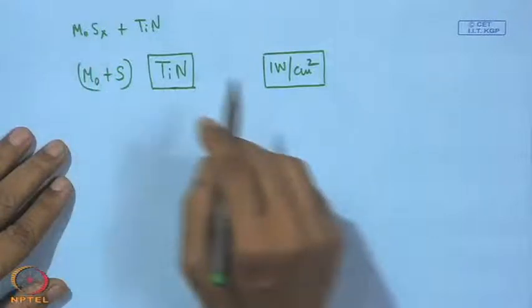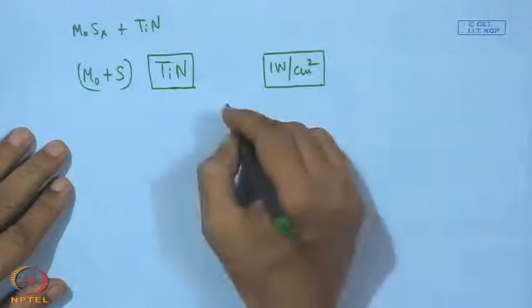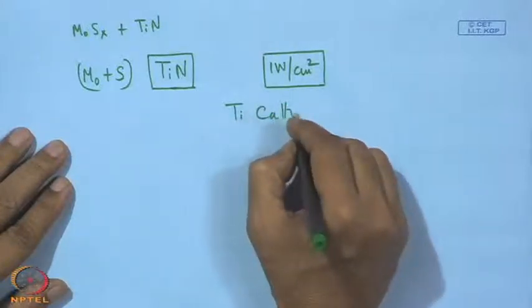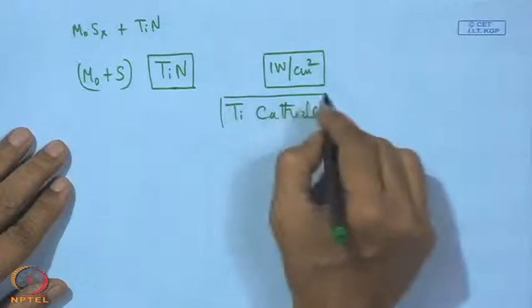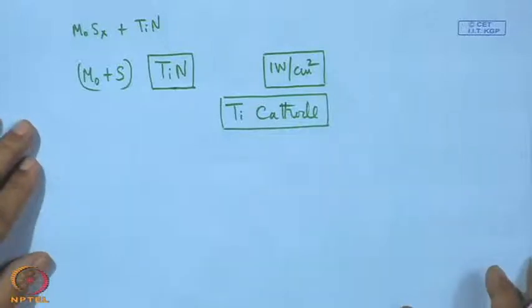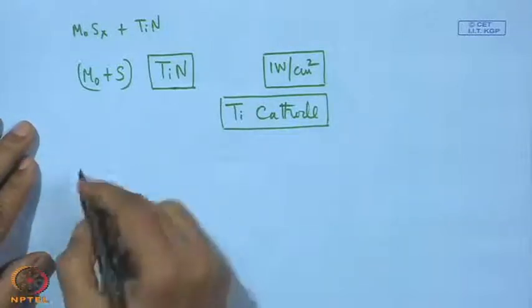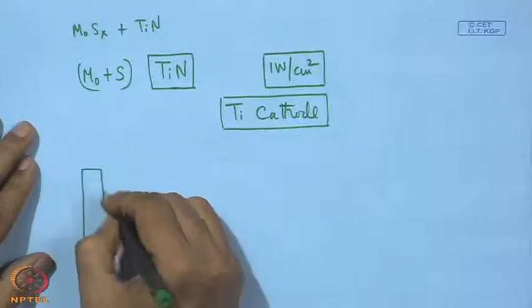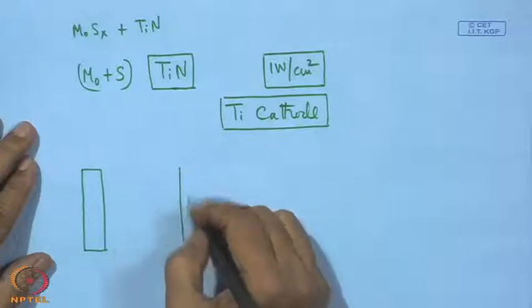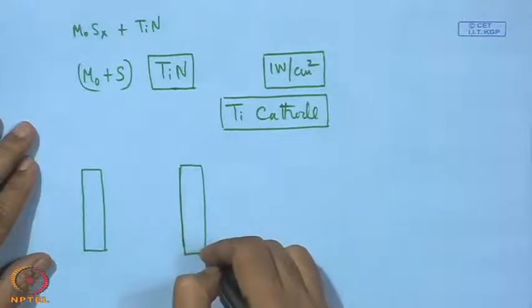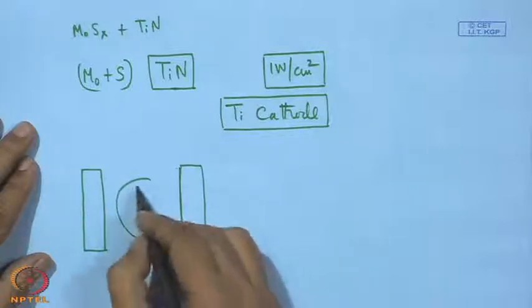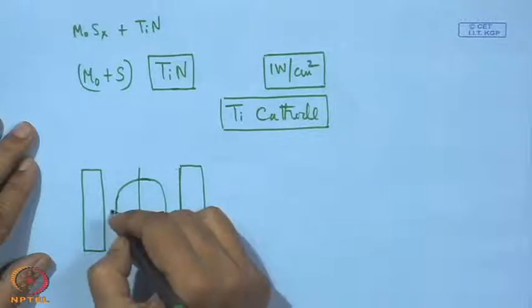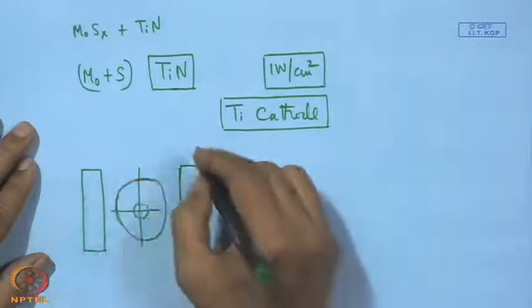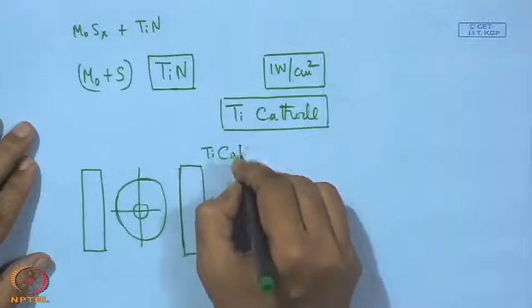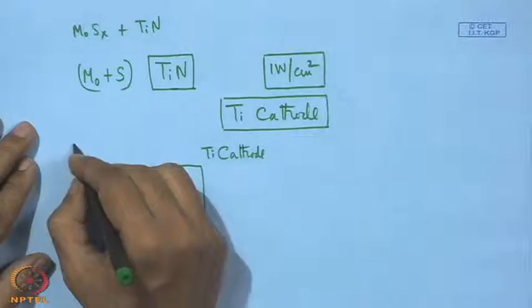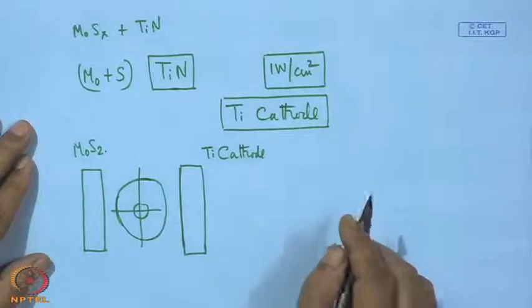On the other hand, what can be handled rather easily is the titanium target, the titanium cathode current, and that has been done. That means in this process, if we consider, it is actually a dual cathode machine. In this dual cathode machine, this is the rotary table, and here we have this titanium cathode and MoS2 cathode.